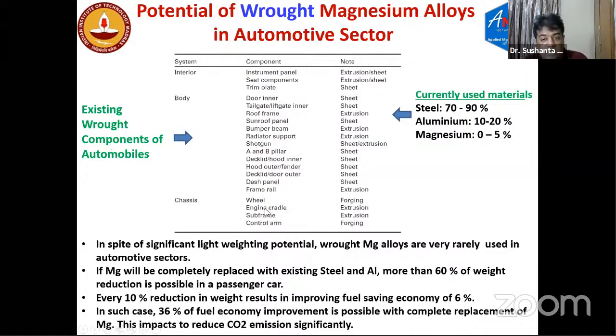The existing wrought components, instrument panel and everywhere. But at present, steel is the leading player. Everywhere they use steel, 70 to 90% steels are used. 10 to 20% of aluminums are used, but only 0 to 5% of 10 to 15%, 20% aluminums are used. Only 5% of magnesiums are used, in spite of having significant potential.